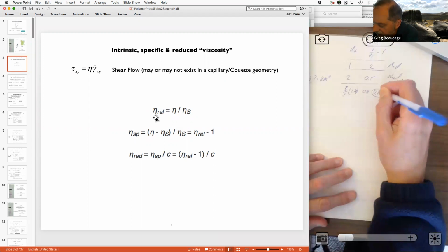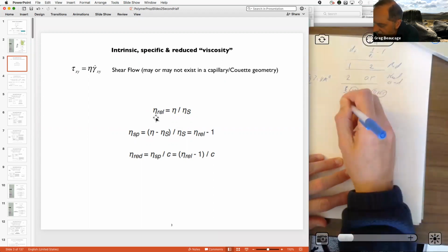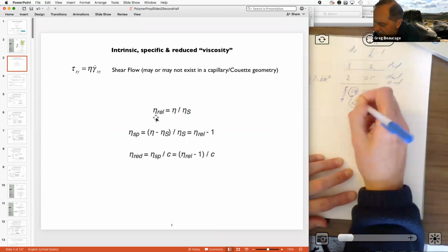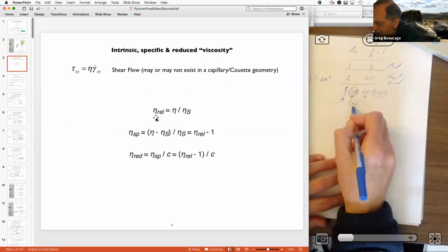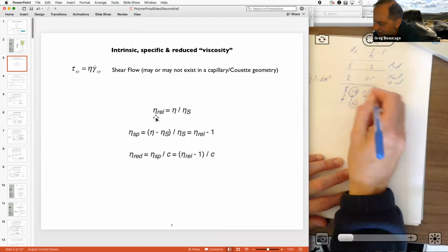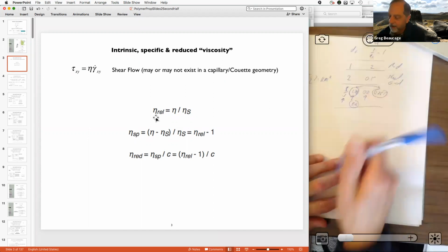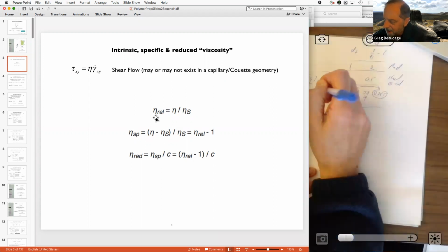Right, so that's kind of the actual number, and this is an approximate number from the Flory-Krigbaum. When you do the Flory-Krigbaum and use an approximation, you get 5/3. If you do a numerical integration, you get 1.7. So these are actually the numbers that probably you should use, but these are easier to remember. Right, so that's kind of how this intrinsic viscosity is generally going to behave.